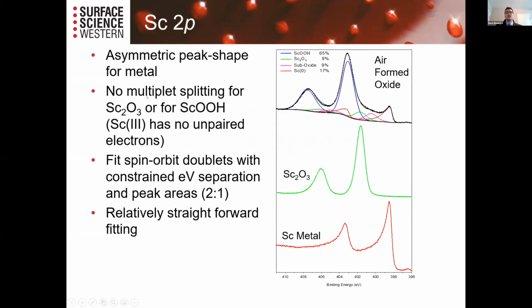So if you look at species without significant multiplet splitting, we can look at some of the reference spectra. We have an asymmetric peak shape for the metal. For the oxide, we have these doublets here, of course, spin orbit doublets that have constrained values of areas of 2 to 1 and specific spacing between those species. And then we can put that all together into a peak fitting routine that takes into account all these things. And then the area under the curve tells us the amount of the different species present.